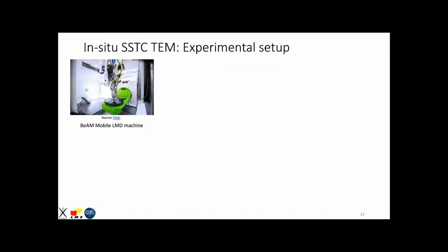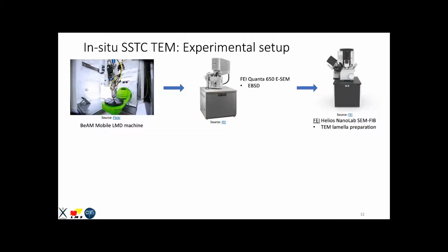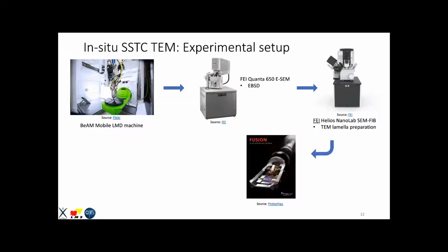But we have solutions for that. Okay, so focusing on the experimental setup, the way we do this is we print our samples in the LMD machine that we have over here in our lab. Then we do an EBSD characterization to understand what is the grain structure, and then go to the FIB SEM that is installed at MSS Mat, where we prepare our lamella from an interesting zone that we figured out from the EBSD maps. We put this lamella on this fusion in situ heating and thermal and electrical holder, which goes